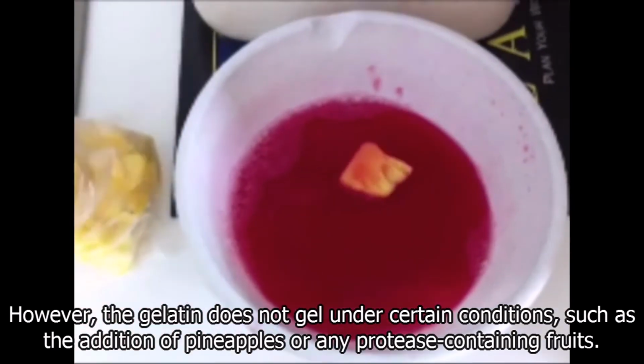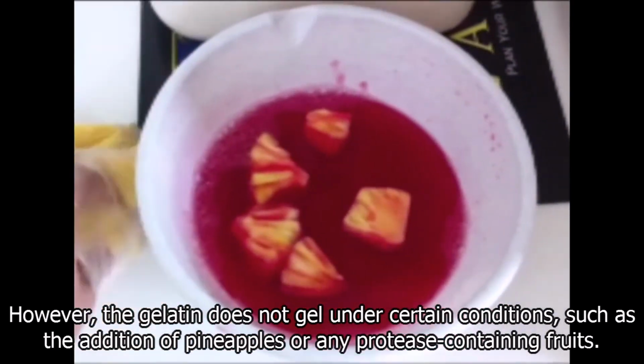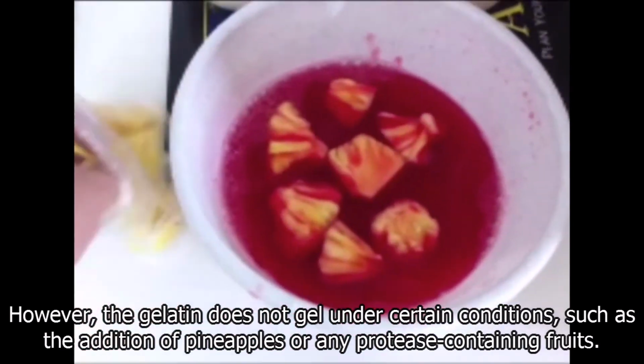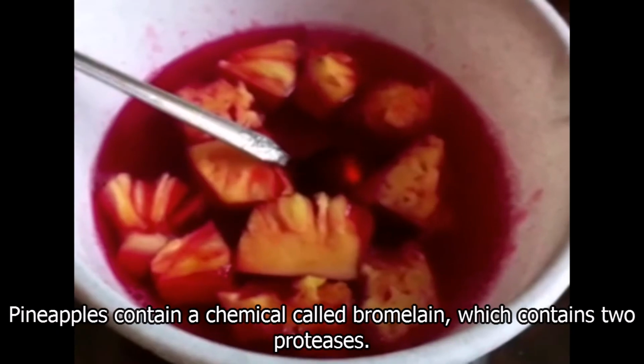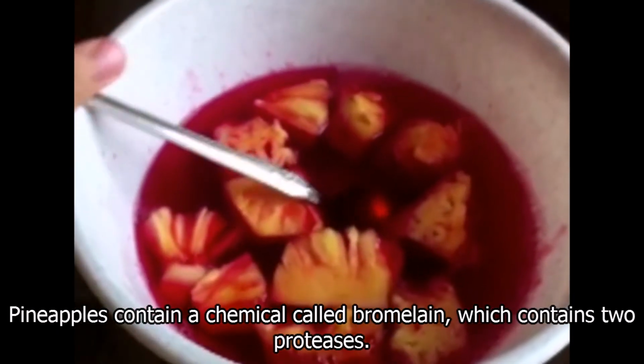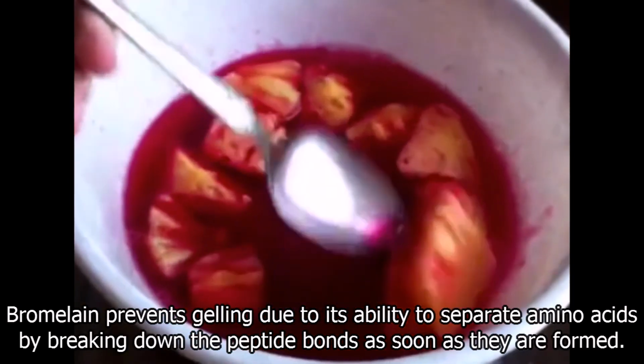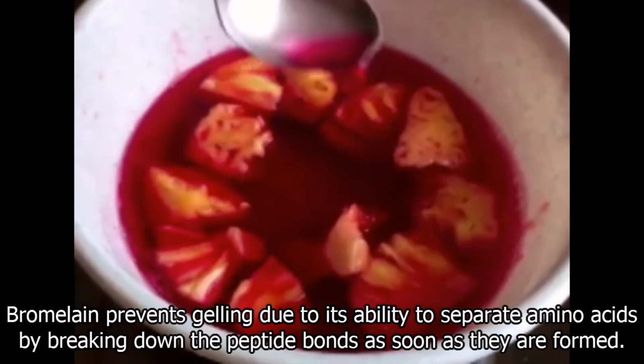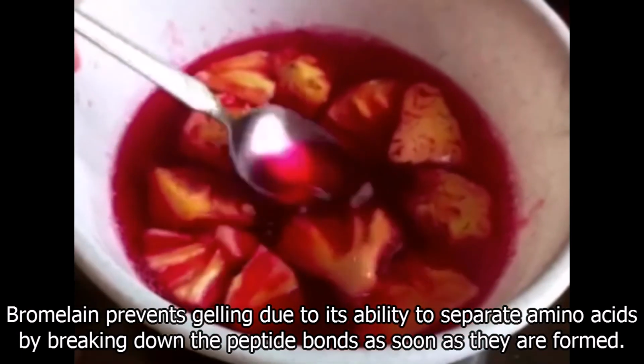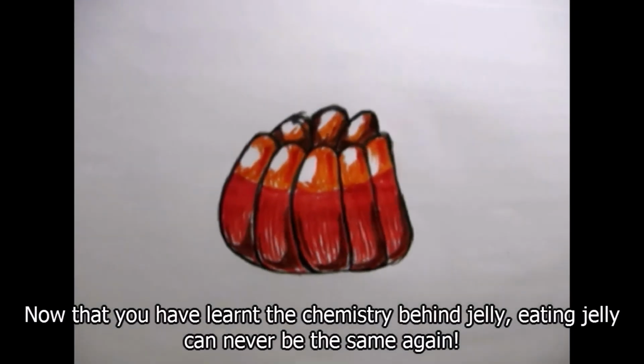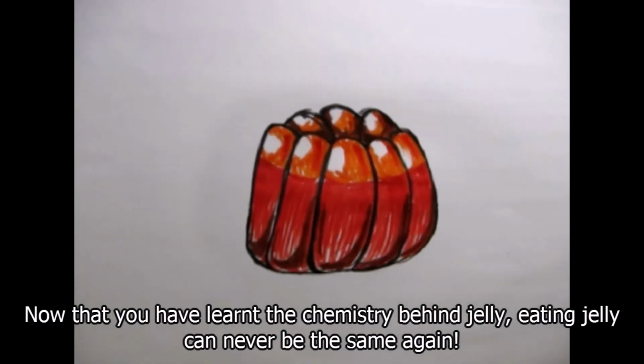However, the gelatin doesn't gel under certain conditions, such as the addition of pineapples or any protease containing fruits. Pineapples contain a chemical called bromelain, which contains 2 proteases. Bromelain prevents gelling due to its ability to separate amino acids by breaking down the peptide bonds as soon as they are formed. Now that we have learned the chemistry behind jelly, eating jelly can never be the same again.